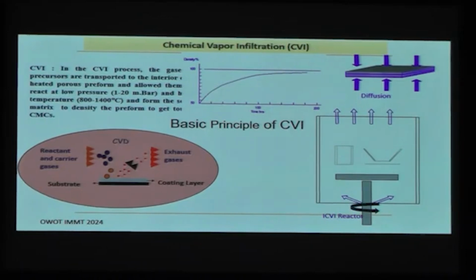When you start with the preform, the free surface area will be more. So first, every individual fiber will be coated. Then after some time the inter-fiber bundle will be coated. And finally, if you keep on doing this reaction, you end up with the full-fledged composite. So this is the densification rate. Typically about 300 to 400 hours of infiltration is required to get almost 88 to 90% of theoretical density.